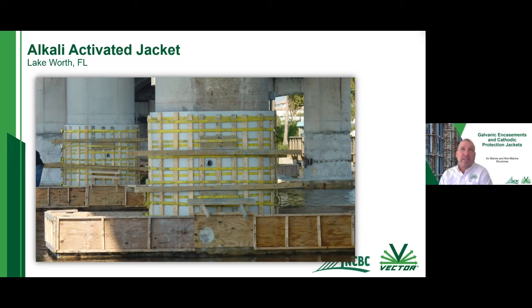The jackets are placed around the column, and they are braced appropriately to keep shape. And you can see that there's pumping ports on this jacket as well. Alternatively, you could have used also a tremie port. You would have ended up using a few different tremie pipes in this as well. When using a tremie pipe, just be sure that the contractor has them secured and they're not going to move and knock a bunch of the wires around or knock a bunch of the anodes around as well. And on the right side, you can see there's a junction box that was being used on this.